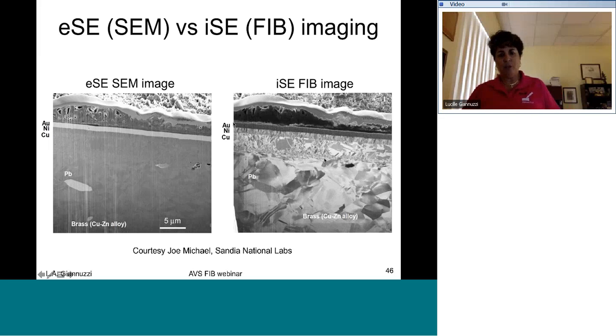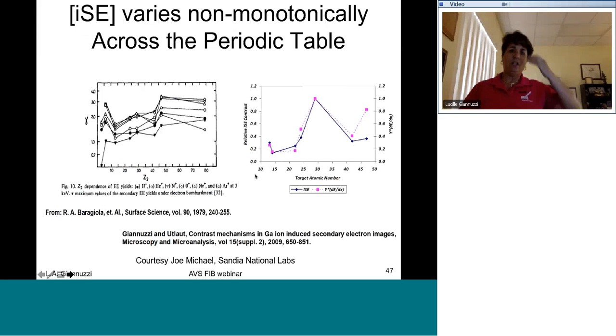Not only that, but you see that the ion-induced secondary electron image can be much more susceptible to channeling contrast. Okay, so here in the brass down here, you're seeing a lot of different contrast due to channeling. You see the lead here is pretty dark. The gold is the darkest, and the nickel here is actually darker than the copper. This is actually quite complex. And what you see is that the ion-induced secondary electron signal varies non-monotonically across the periodic table.